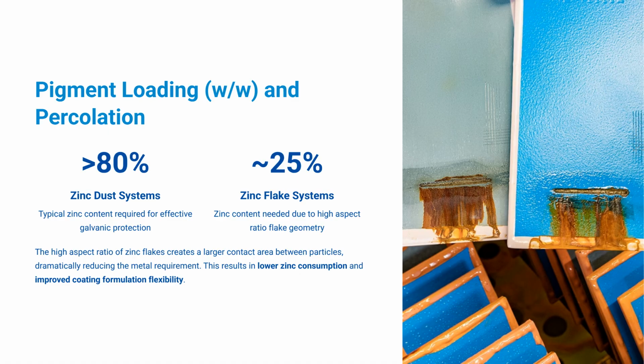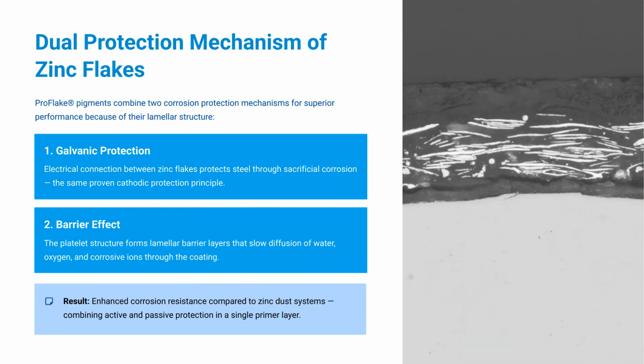enhanced coating performance. One of the major advantages of zinc flake technology is that it combines two corrosion protection mechanisms within a single coating. First, zinc flakes provide galvanic protection through electrical conductivity and sacrificial corrosion, the same cathodic protection principle used in traditional zinc-rich primers.